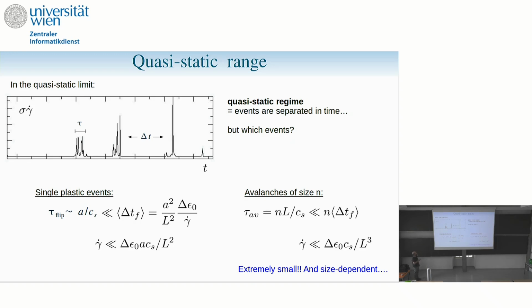If you think events are just single events, the separation means that the time of a rearrangement is smaller than the time between events, and that tells you that you have a limit strain rate which scales like 1 over L squared. You can do the same thing for avalanches of size n. If you consider that to have an avalanche, you need the signal to go through the whole length of your system a number of times, again you find a criterion that the strain rate has to be smaller than something like 1 over L cubed. And the problem is that these limit strain rates where AQS conditions are relevant depend on system size. That tells you that the AQS conditions are not relevant in the limit of large system for any finite strain rate. So what did I say which is misleading?